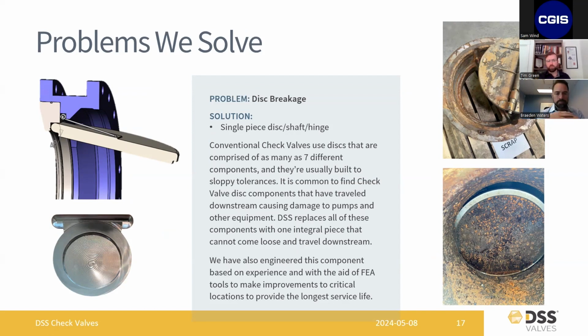One of the primary failure mechanisms that we see with check valves across all industries is disc breakage. On the right here, I've got a couple of photos. This is a traditional dual plate API 594 wafer check valve. The discs on these valves, if you'll notice, have 6 or 7 different pieces. There are spacers between all the parts, and the hinges, hinge pin and springs are very prone to breakage going downstream. So you lose your disc in your check valve. Now you don't have a check valve. You have a spool piece, potentially. It's just going to allow free flow in both directions, which could be catastrophic to other equipment or even operator safety.